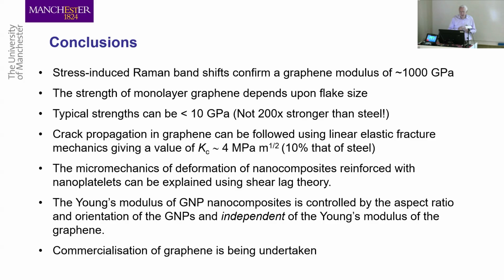We can look at the mechanics of deformation quite nicely, explain everything using conventional shear lag theory. And it seems that the most important factor that controls the properties of these 2D materials is aspect ratio and orientation rather than the inherent mechanical properties. And a lot of people are trying to commercialize graphene. We did an upmarket commercialization, but there are many other ways of commercializing the material which are taking place in Manchester.